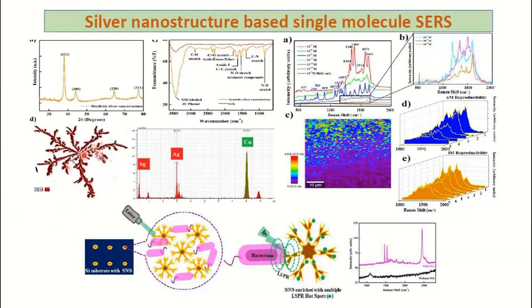So you can see these structures basically with more and more junctions. What happens? The hotspots are increased, and once the hotspots are increased, the sensitivity, the enhancement factor, also increased. Previously we have shown that the enhancement factor was 10 to the power 9. Now we have achieved an enhancement factor up to 10 to the power 12 and 10 to the power 15, and that's why we can detect femtomolar concentration, and in femtomolar concentration also you can see the reproducibility. So everywhere you hit, you can detect the analyte.